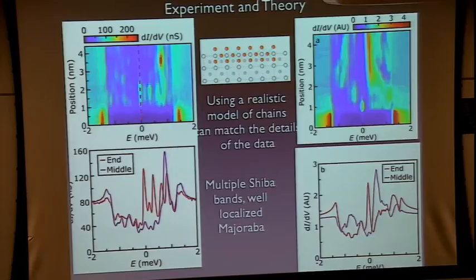Edge modes. That Andreev state at the edges, Majorana states at the end. That's the only distinction you have. Or how it responds to disorder. But the disorder makes it have in-gap states. Or you make some sort of a pi junction and measure the pi phase shift. Those are the different ways to distinguish.